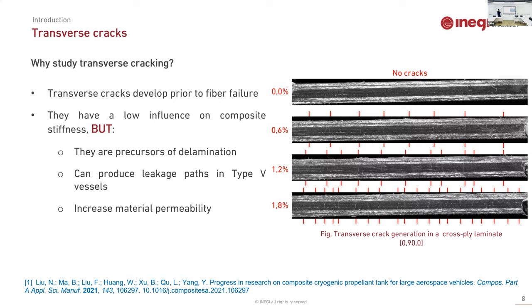What is important? In general, the transverse cracks have a very low influence on the stiffness of the material, because the stiffness and the strain are given by the fibers, not by the resin. But these transverse cracks are precursors for delamination that will lead to catastrophic failure depending on the structure. Looking at pressure vessels, they can form leakage paths for the fluid and could also increase the material permeability if we are storing acids or any kind of material.